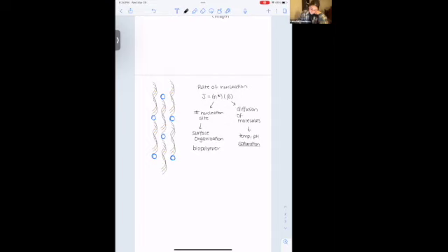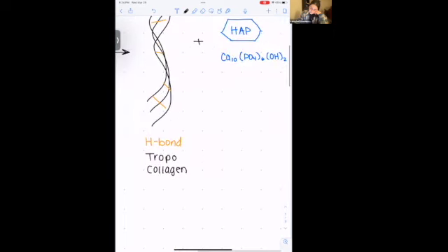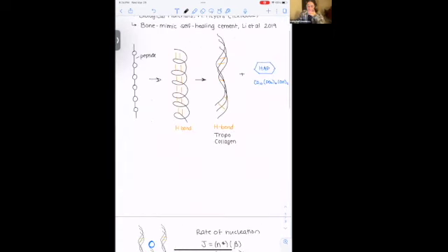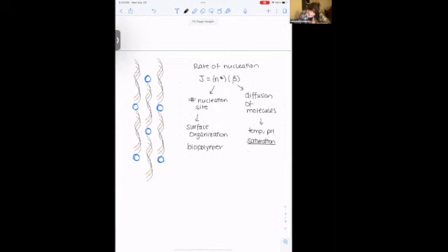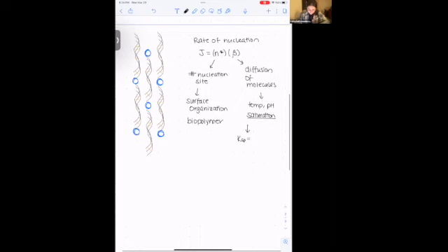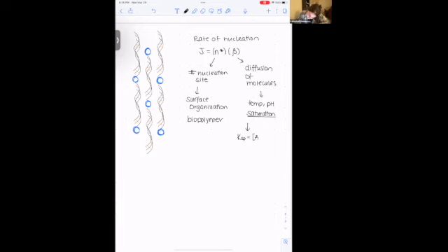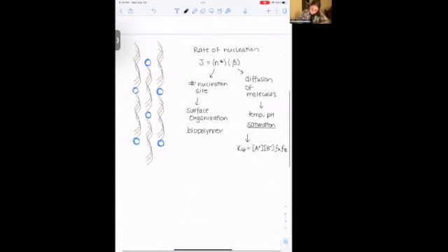And so for this hydroxyapatite, as you see up here, we need the calcium, the phosphate, and hydroxide groups. A key term for saturation is the solubility constant. And the solubility constant describes the value at which that nucleation will occur. And it depends on the concentration of your different components and their activity coefficients. So that describes how the nucleation will occur.